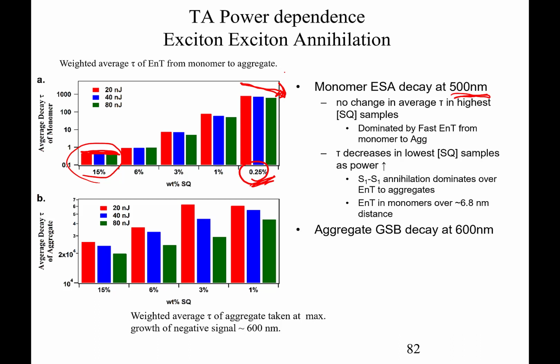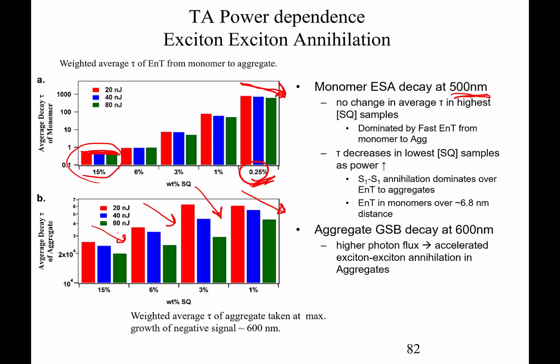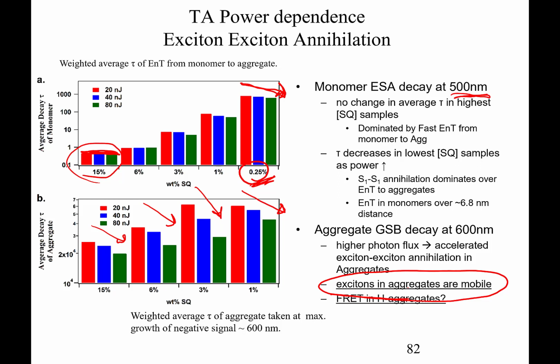What happens with the ground state bleach at 600 nanometers? In this particular case, we see quite substantial pump power dependence. We see these lines in here, and this basically tells us that these excited states in these aggregates are actually mobile. They move around. We definitely get exciton annihilation once these aggregate states are formed. So the crazy thing here, this is not expected, but the important thing to recognize is that excitons in these aggregates are indeed mobile.